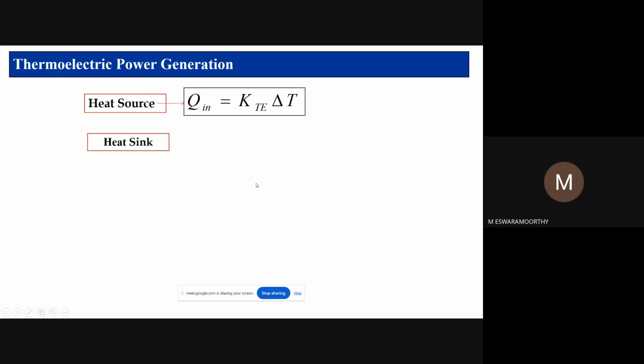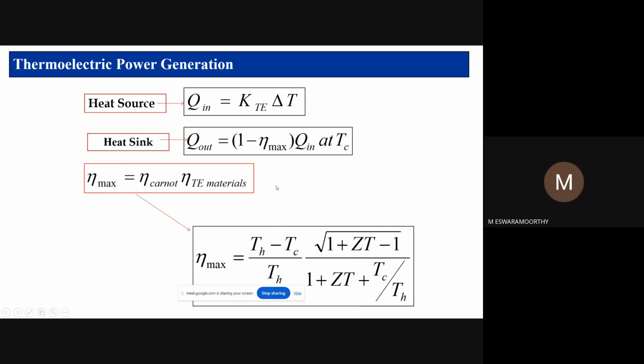This efficiency terminology is calculated with simple correlation equations, as in your heat and mass transfer. The heat source, the thermoelectric material's thermal conductivity, the temperature difference across the source and the heat sink determine the maximum possible heat transfer, and we can easily calculate the efficiency. That is the Carnot cycle efficiency, Th minus Tc by Th. The thermoelectric material has a different efficiency terminology based on ZT, called the thermoelectric material efficiency.